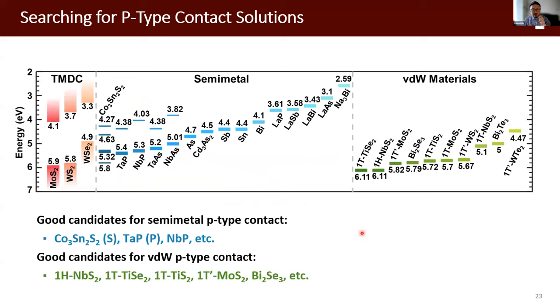And another direction we are working on is to search for good P-type contact solutions. So we did a computational screening, and I tried to figure out the band alignment between the 2D semiconductors and a variety of semi-metals or topological semi-metals, as well as different van der Waals materials. And for P-type contact, we want the work function to be at least about 5 electron volts, especially if we want to work on tungsten diselenide. And we have identified a couple of good material candidates to form the good P-type contact.